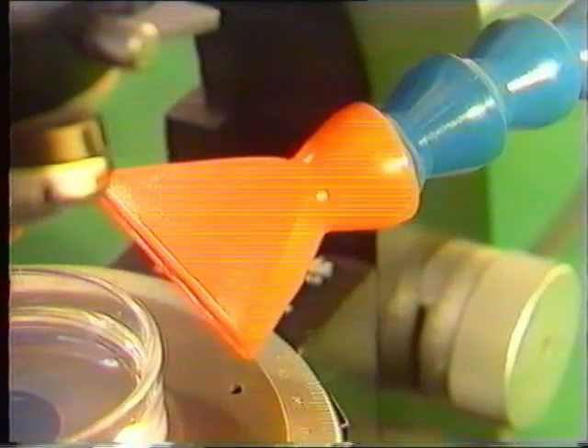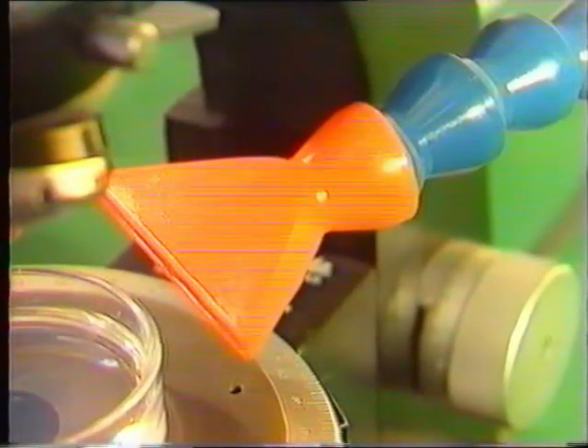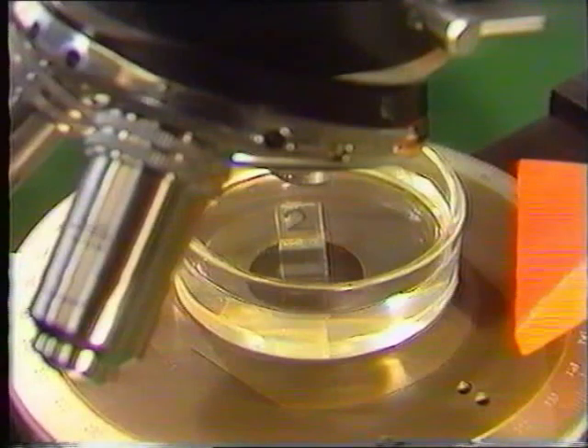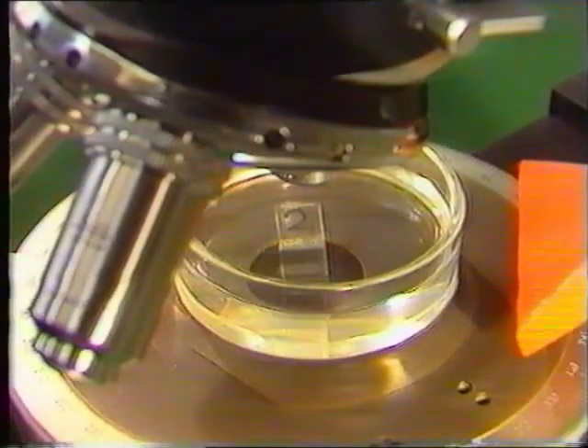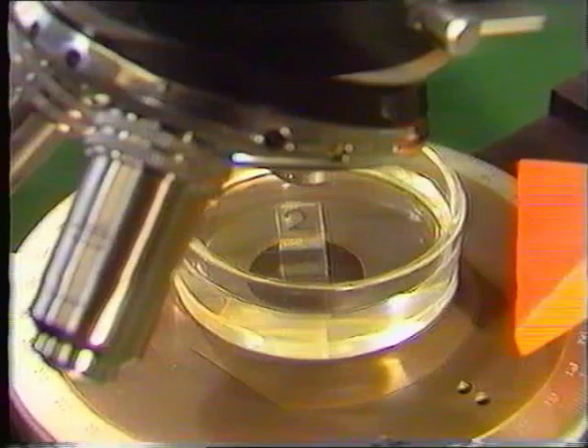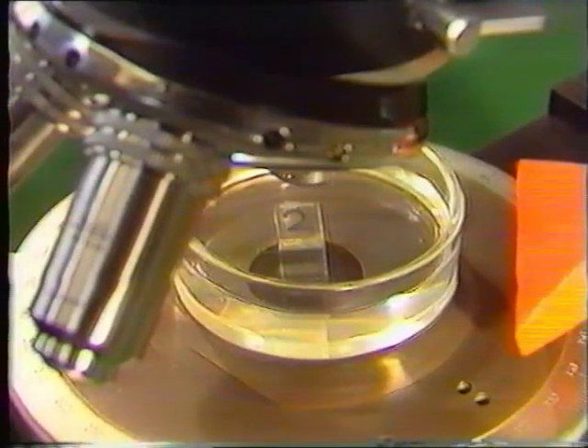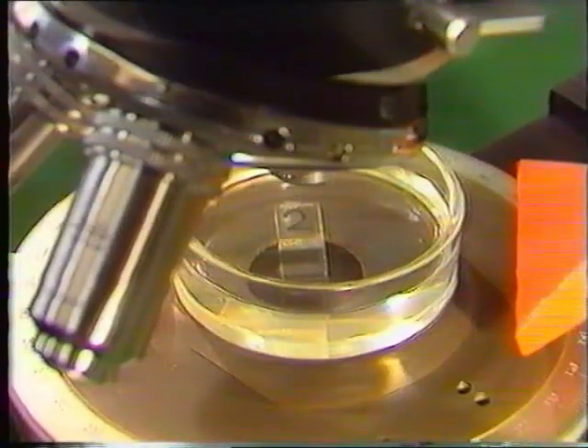For the test, exhaustion of toluene fumes is necessary. The standard glass is pointing to the analyst. Remember that the microscope, except the Leitz Diavert, inverts the image. Left becomes right and top becomes bottom. The measuring location is determined with the diaphragm open. The dark shadow lines, more or less perpendicular to the dividing line, should be made to intersect with the line on the cuvette by moving the cuvette in the direction of the dividing line.